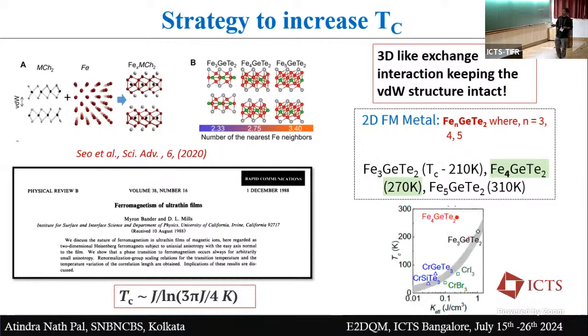Now, one more interesting thing is that in this paper, they looked at the anisotropy, and they saw that if you increase the anisotropy in this material, the TC increases. That is following a trend, except in this material, where the anisotropy is low but you actually have a higher TC. So that is a puzzle in this kind of F4GT material.